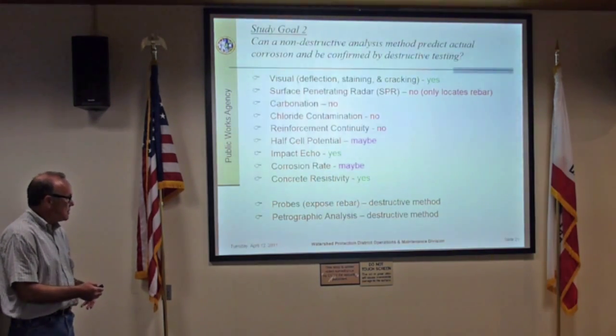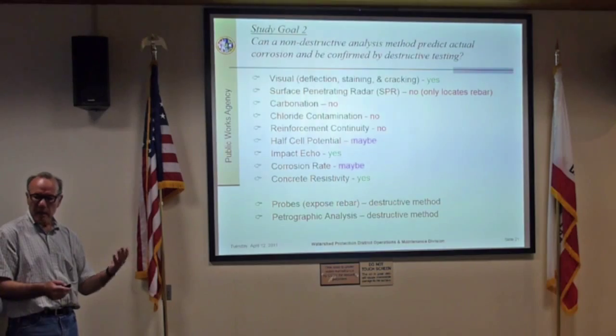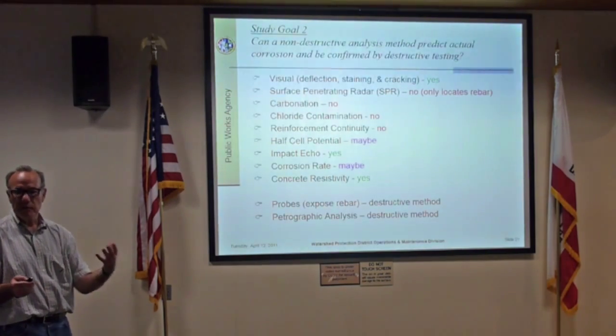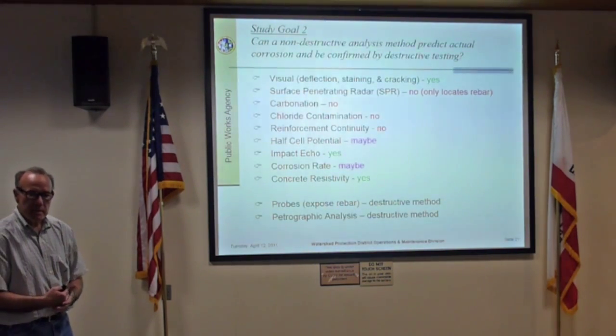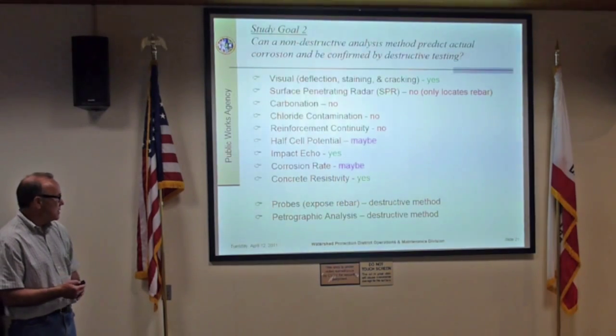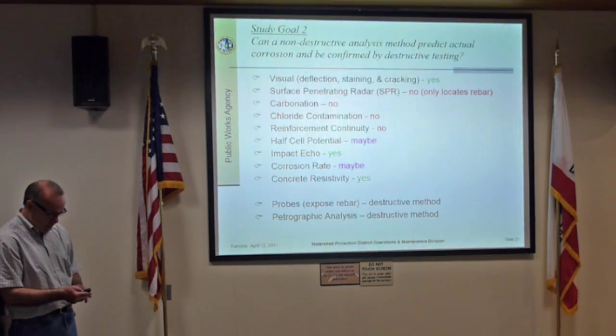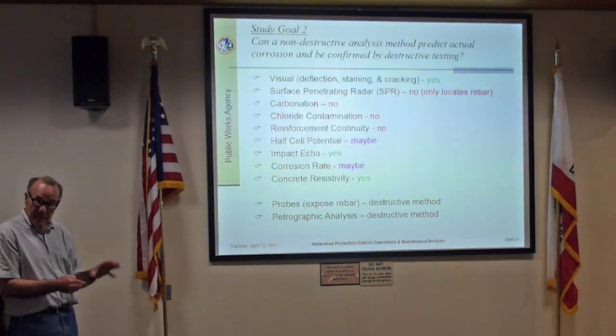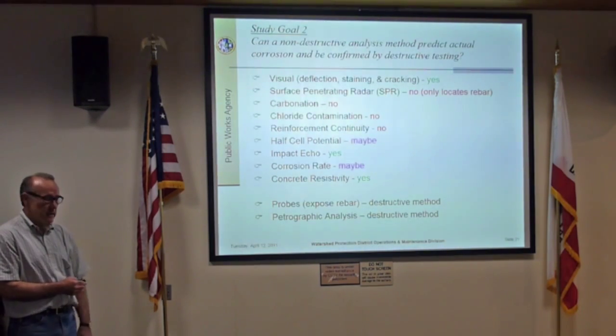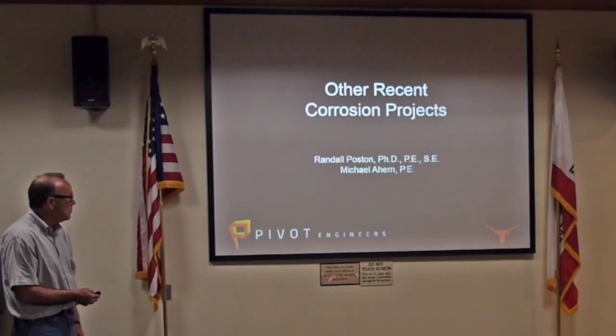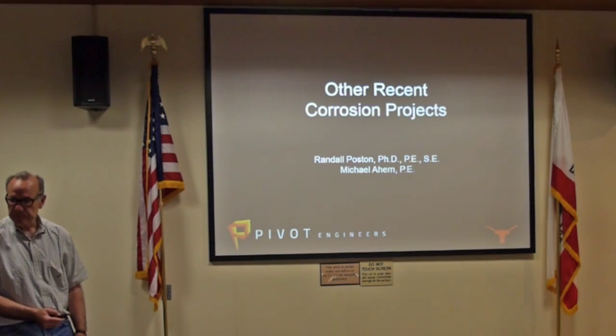Petrographic analysis: we wanted to make sure there weren't other outlying mechanisms like ASR. We did find some trace elements of ASR, alkali silica reactivity, in this concrete, but it wasn't so extreme that in these channel walls we were necessarily concerned about it from a moving forward perspective.